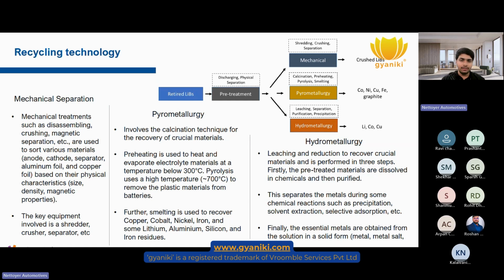In the single shredder, a lithium-ion battery pack consists of plastic material. It consists of aluminum as well as nickel. It consists of copper and the black mass. 45% to 50% of the lithium-ion cell constitutes plastics, metal parts, and copper and nickel. And then the remaining 55 or 50% of the lithium-ion cell consists of black mass.